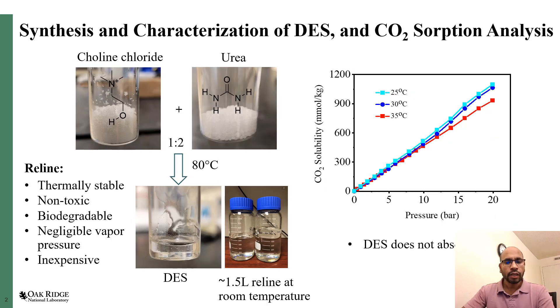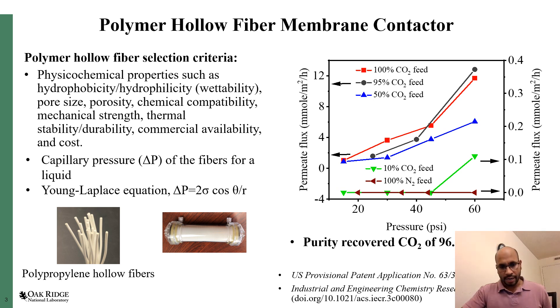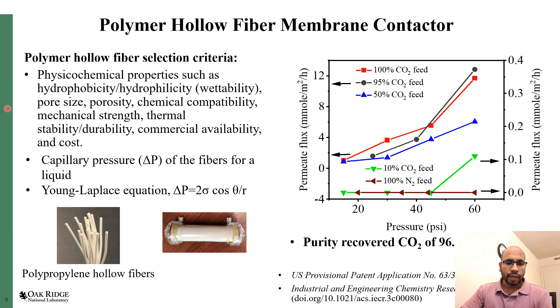As a starting point, we used reline, which is made of choline chloride and urea. To establish the proof of concept, after synthesis we analyzed sorption measurements. The results show that CO2 solubility increases with pressure almost linearly, confirming it is a physical sorbent, while it does not absorb any nitrogen. For a membrane contactor process, two important criteria that must be met are wettability and capillary force.